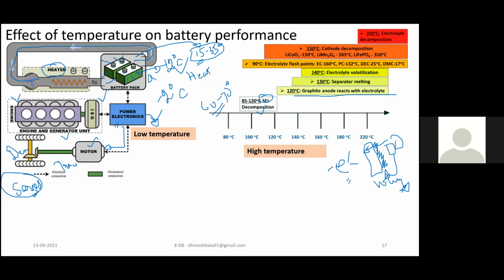And at 130 degrees Celsius, the separator would start to melt. So the separator is nothing but the center layer present in between the electrolyte. So this would also be an added barrier for the movement of electrons in the horizontal direction. And at 140, the electrolyte volatilization would start to happen. And at 150, the cathode decomposition would happen.